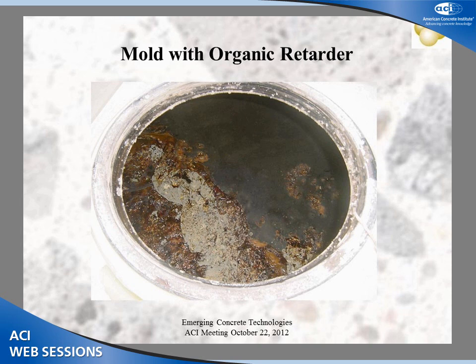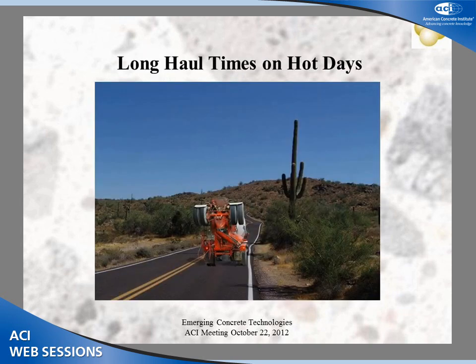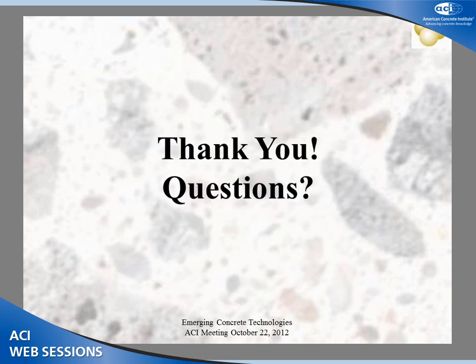This will just give you an example of what happens with conventional retarders when the fungicide wears off and bacteria attacks the organic retarder. This would not happen with zinc oxide. Okay, so that is a big plus with the use of zinc oxide because it is an insoluble inorganic material, and it is highly suitable for a situation like this where you've got a lonely ready-mix driver on a long desert-like road. Could be 1 or 2 hours away from the pour.